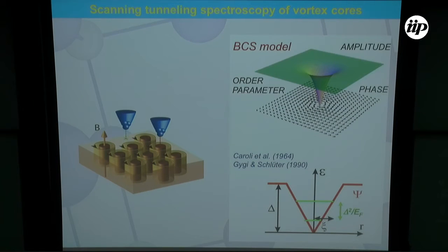So again, the order parameter is singular at the position of the vortex, and in a way it's a kind of potential well, where you have quasi-particle bound states, and the spacing, which was calculated by Caroli in the 60s, is of the order of delta squared over E_F, which is a very small quantity. And actually, with the STM, the spacing between these states is not measurable, since the temperature is broadening all these effects.